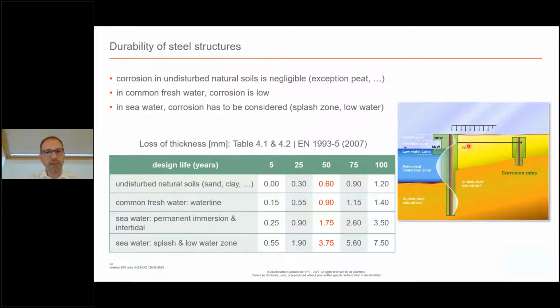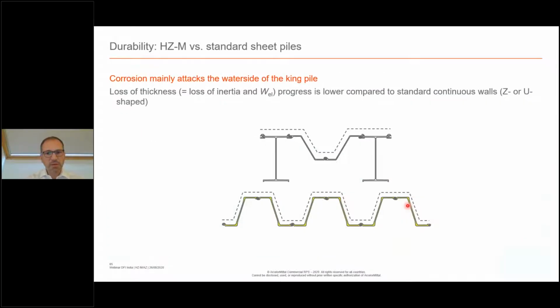And by playing with the length of the pile, but also the position of the anchor, you can change the position of the maximum bending moment so that it will never be in one of those very highly corrosive zones. However, there is a small difference between a combined wall system and a standard sheet pile. Imagine that you have a waterfront structure, so the water is more corrosive than the soil, so you have less surface in contact with water than compared with the standard Z pile.